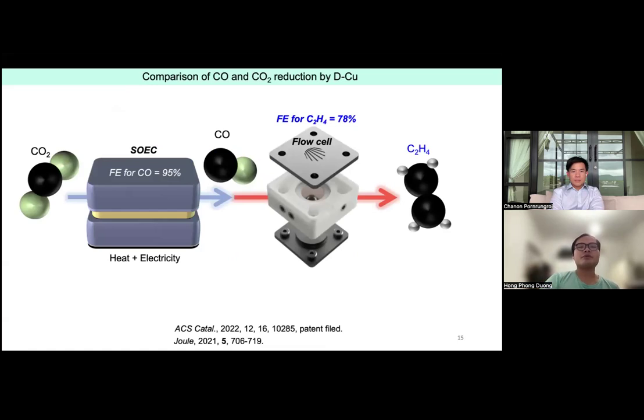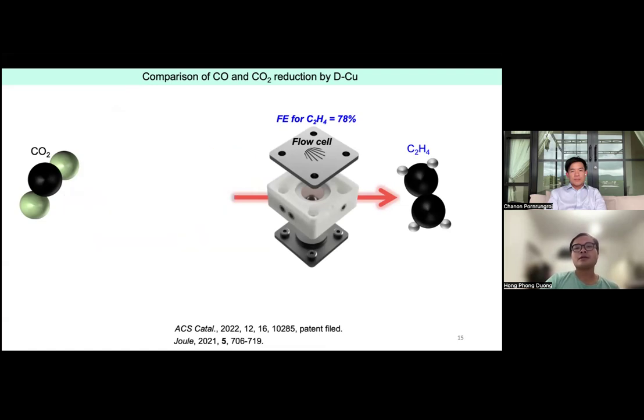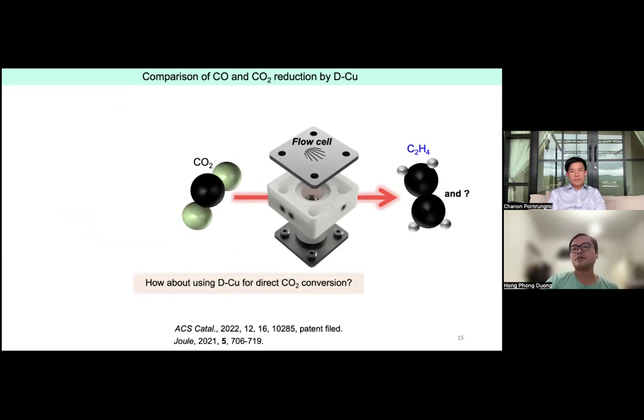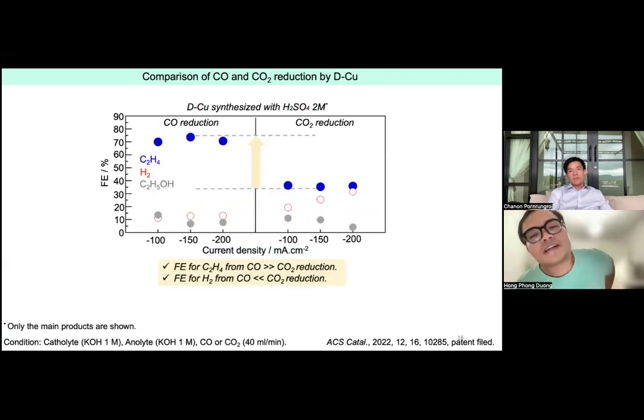Then we were thinking, let's make a comparison between CO and CO2 reduction by this catalyst. We utilized this directly for CO2 reduction to see, imagine if these can also make very good ethylene from CO2 reduction in this flow cell, it would be even better. But we found that by CO2 reduction, in fact, the efficiency for ethylene was much lower, just around 40%, and we got more hydrogen in this case as well. So this again highlights the difference between these two reactions using this catalyst.